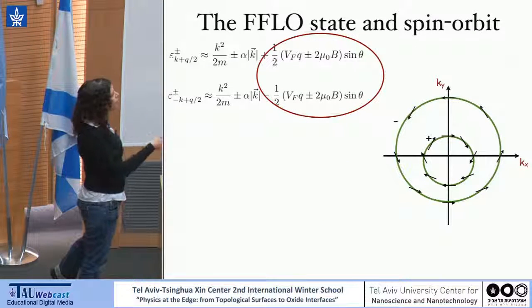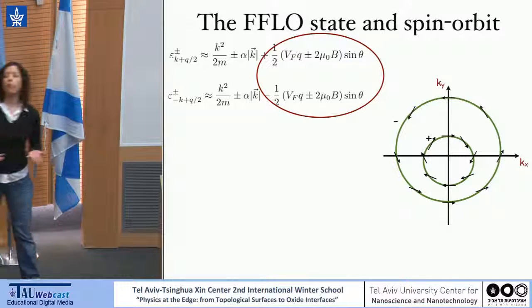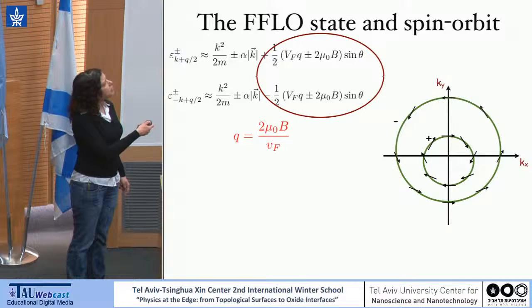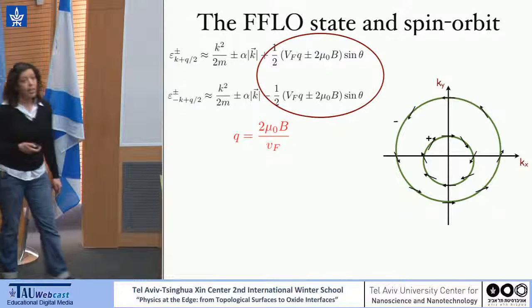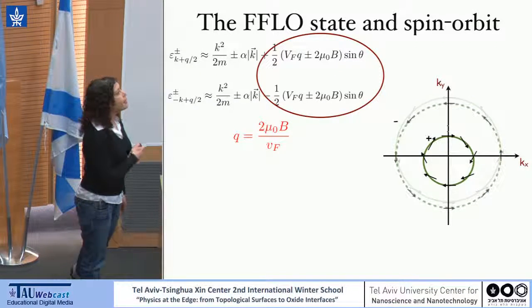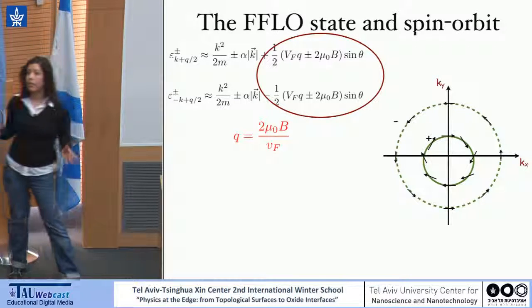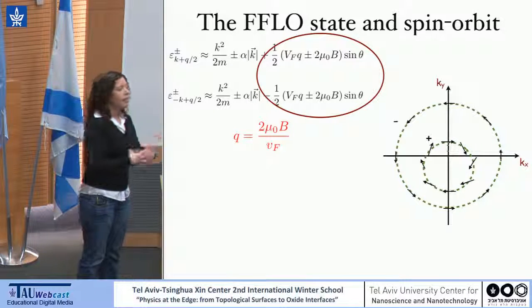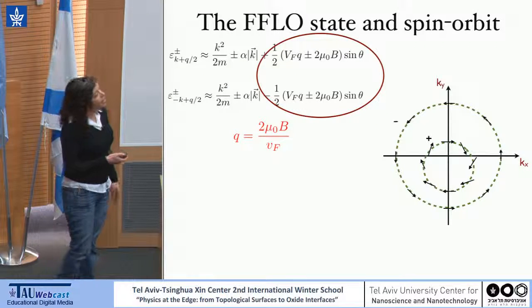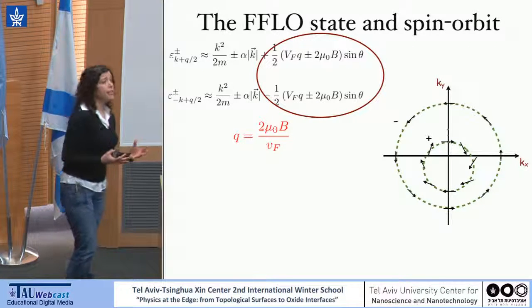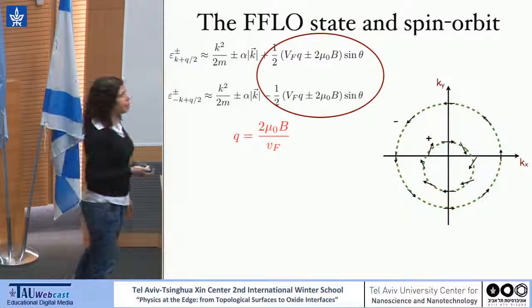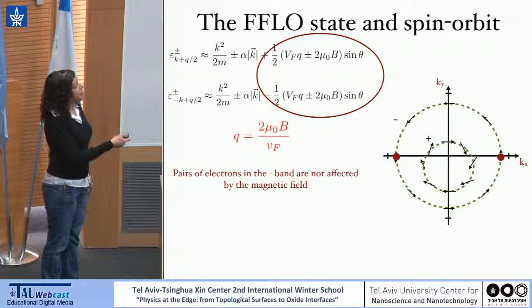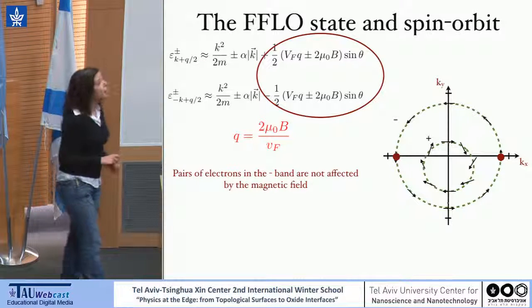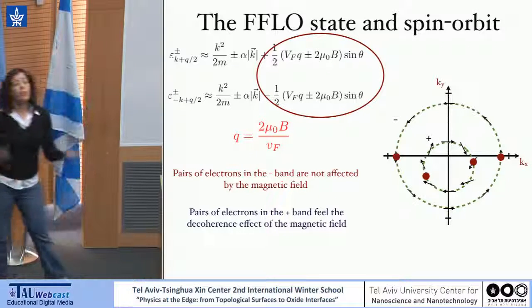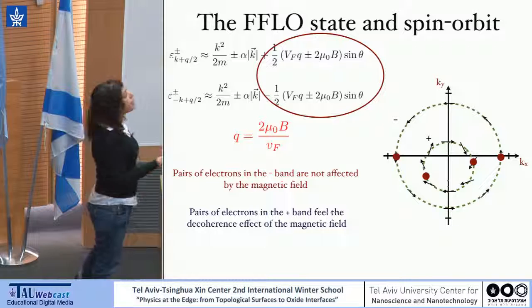However, there is a small problem: we have plus and minus that just refer to the two bands, and therefore we cannot eliminate the effect of the magnetic field from both bands, but only from a single band. So if I choose q to just cancel this term for the minus band, we will see that the pairing on the larger Fermi surface becomes perfect, again, as if we don't have a magnetic field in the system. However, for the lower band, everything becomes a bit worse. But since the density of states is very different for the large Fermi surface compared to the small Fermi surface, as long as energetically it helps us more to pair electrons with finite momentum on the outer Fermi surface compared to the energy loss on the small Fermi surface, we will get superconductivity, which is at just finite momentum pairing.